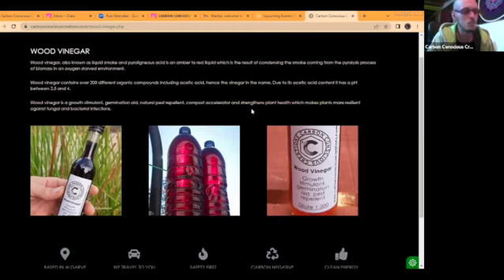But you do have control over the temperature by the way you feed the fire. If you feed it with very loose branched material, very thin sticks and stuff, it's going to be hotter. If you give it a bit thicker material, like let's say 5-6 centimeters diameter sticks, then the temperature is going to drop a bit, because there's less active surface area involved in the fire at that time.